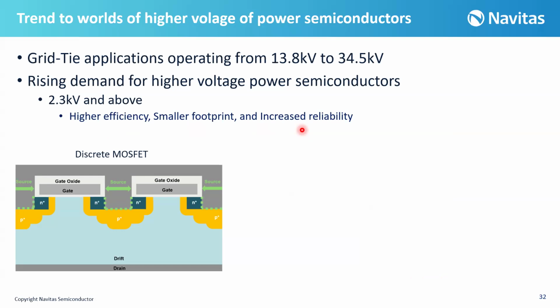However, when we are increasing the voltage, it means that we need a thicker drift layer. One challenge in silicon carbide is the basal plane dislocations, or BPDs. When we have a high current in the PN junctions here in the body diode, we may get conductivity modulation where we have both electrons and holes, and these electrons and holes can recombine at the BPDs, forming stacking faults. And these stacking faults grow at a 4-degree angle, because normally we are using 4-degree off-axis silicon carbide these days.